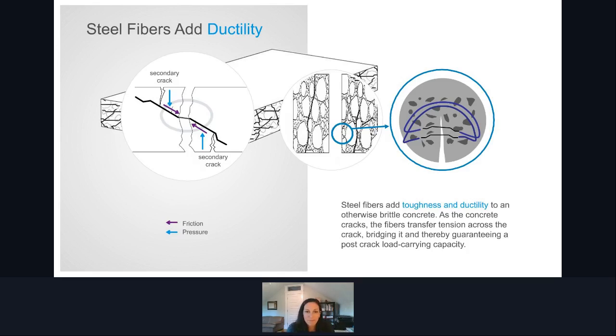Concrete cracks. So when a crack occurs with this full depth, even distribution of fibers, you can expect a fiber to be close to that crack and arrest it immediately. Once that happens on a local level, that fiber will be engaged in tension and will anchor itself at its anchorage points. With Dramix, we have end deformations or different kinds of anchorage mechanisms out there. So in this case, where it anchors, it's going to develop a localized stress at that anchorage zone, which will lead to a secondary crack.